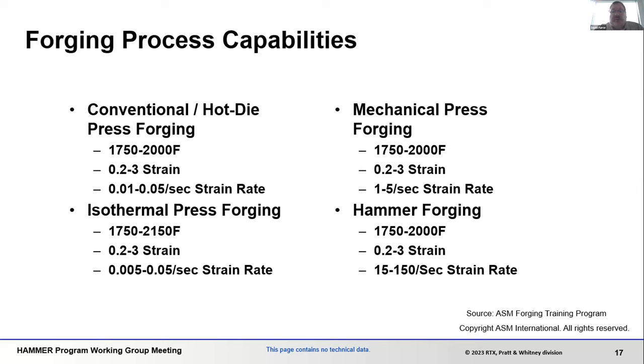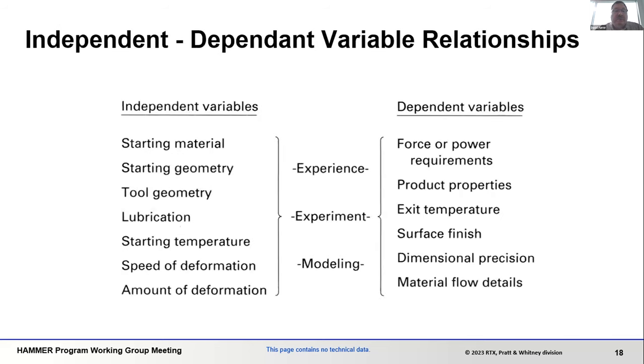Mechanical presses, like we just saw, again, different temperature ranges, very high strain. Intermediate strain rates, now pretty high, up to as high as, say, 5 per second. It's a pretty high strain rate. And hammer forging, now going to a higher strain rate yet, of like 15 to 150 per second. So very high strain rates. If you start doing those kinds of strain rates at mechanical press strain rates or hammer strain rates, you have to start worrying about adiabatic heating, and things that can occur because of the adiabatic heating. And I'll show you some of that in a minute through some modeling activities.